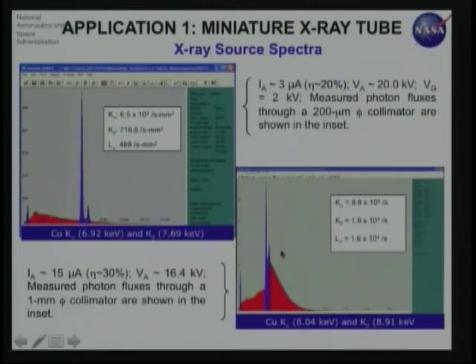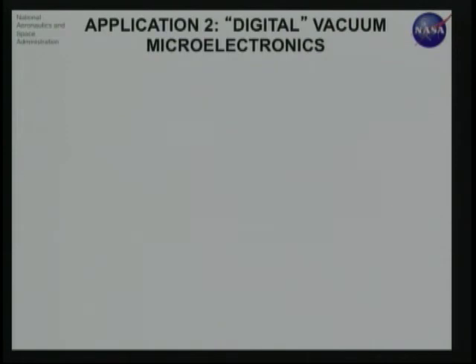And the same thing for copper, at a slightly higher efficiency, with applied voltage about 16.5 kilovolts. You see the copper K alpha, which is about 8 kilovolts, and K beta, about 8.9 kilovolts. You have a sufficient photon flux coming off, and this is an unoptimized source, so when you optimize it, you expect it to work better.